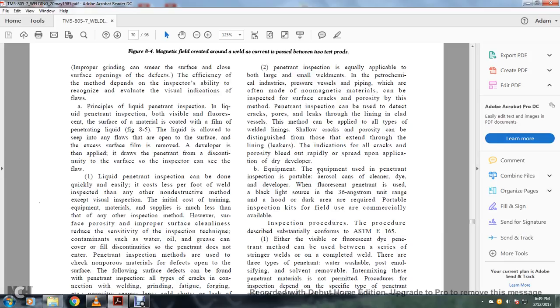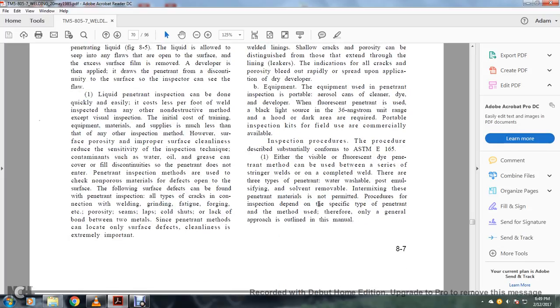Equipment used for penetrant inspection includes portable aerosol cans of cleaner, dye, and developer. Fluorescent penetrant is used with a black light source in the 3600 angstrom unit range, in a dark area, and requires portable inspection kits, which are commercially available. Inspection procedure: the procedure described substantially conforms to ASTM E165.